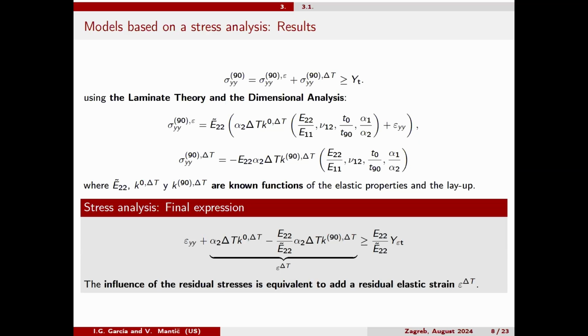And if we rearrange all of this, we obtain this, where you can observe the mechanical strain. Okay, that is the mechanical strain that you are imposing with the machine. And here we have a term that comes from the laminate theory. And this term, we can assume is some kind of equivalent strain due to the residual thermal stresses.